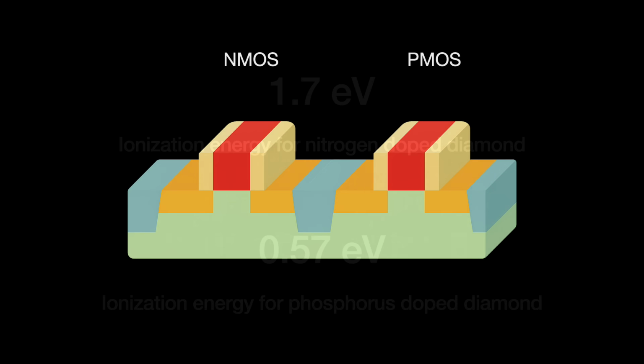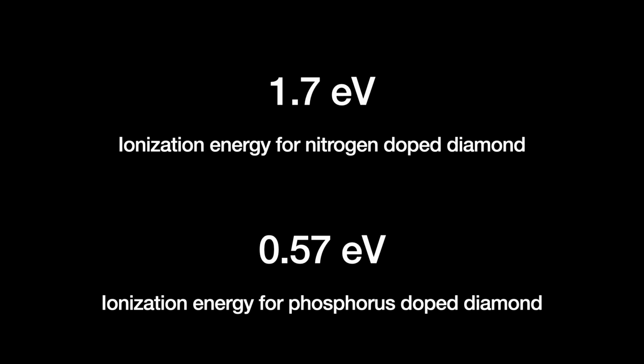Unfortunately, the challenges there are even more daunting, since the dopant phosphorus activation energy is a magnitude deeper than boron, and the only other option is nitrogen, whose activation energy is a freaking 1.7 electron volts. The doping issues around diamond were so bad that it derailed technological progress in the field, with investment and effort going to silicon carbide and others.